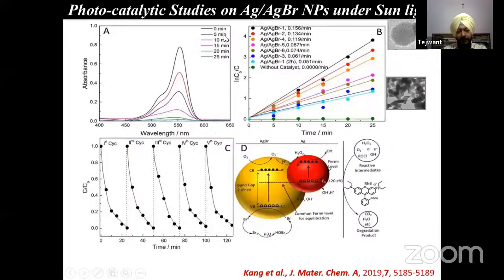One can see from the absorbance spectra in panel A that the absorbance for rhodamine B goes on decreasing, and it almost vanishes at about 25 minutes of irradiation. The important point is that we have done all this photocatalysis under sunlight.